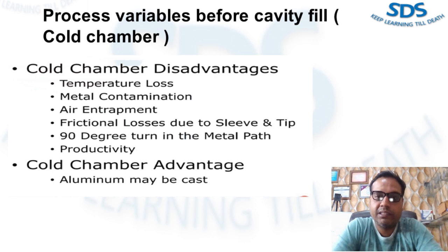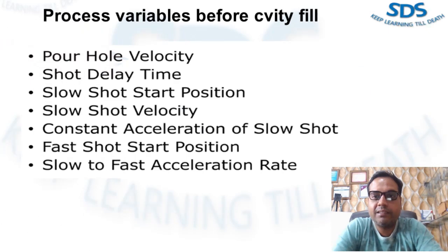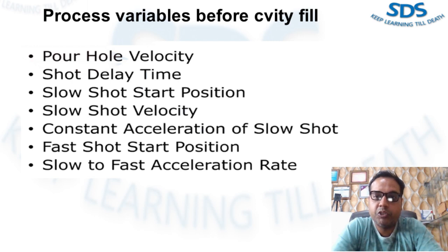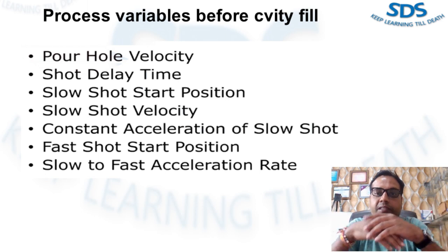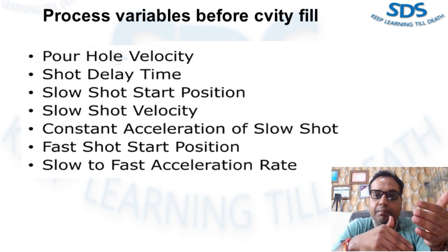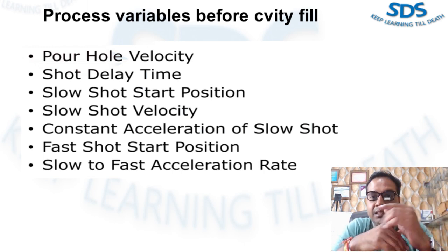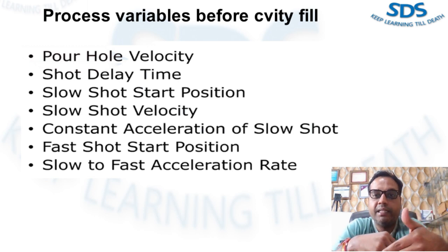The first parameter is shot delay time. The shot delay time is the amount of time from when the ladle has completed pouring into the cold chamber to when the shot motion begins. This time should be dictated by the amount of time for the metal wave within the shot sleeve to travel to the parting line and then return to the shot tip. The shot motion should start at the instant the metal wave hits the shot tip. This time should be tested during process development and then controlled during production by the PLC and documented within the process setup book.